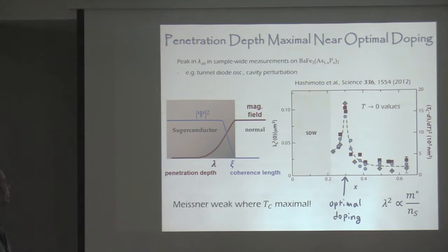And this is a really weird measurement because you can see that there's a very clear peak here at optimal doping, which is kind of counterintuitive because it tells you that, in a sense, at the very doping where superconductivity is the most robust, in this material, it's really the worst because a superconductor's main hallmark is the Meissner effect, and this tells you that at this doping, this material can least expel magnetic field. So this was very curious, and we wanted to